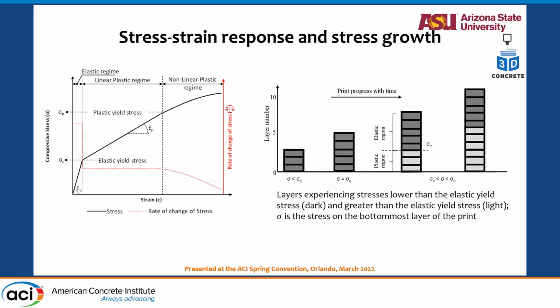If I have only 3 layers built up, as an example, all the stress in the lowest layer is less than this elastic limit because there is not so much load. But if I keep building up, I'm going to see these layers getting into this zone. So that is the way in which we qualified. I'll show you the test method that we have done.